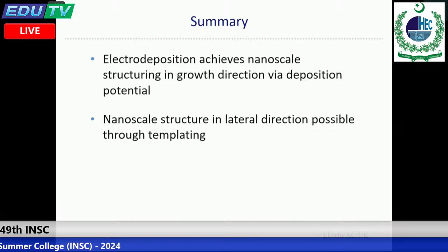So the potential is important, because through the potential you can change what material is adsorbed to the surface. This goes back to a question which was asked in the last lecture. If the adsorption is an electrochemical adsorption, then potential is key. Potential also affects the movement of the atoms on the surface. You can't say only potential is important. Current is also important, because if you have deposition which is too quick, then you don't get close enough to equilibrium.